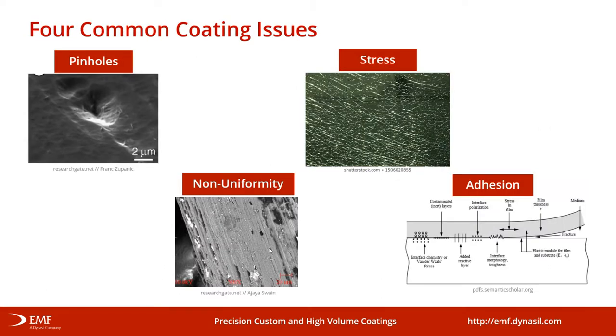In coating optics, there are usually four different coating issues that are fairly common. One is pinholes, which are small little holes within the coating. Another is stress, where the chemical bonds within the coating are creating a stress between the different molecules and can actually crack and destroy the coating. Non-uniformity is where the coating is not the same thickness throughout and causes different effects. And finally, adhesion is probably the most difficult issue, and this is where you actually have problems keeping the material and the coating sticking to one another.